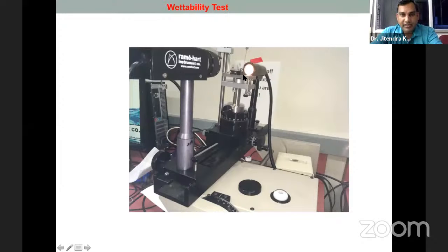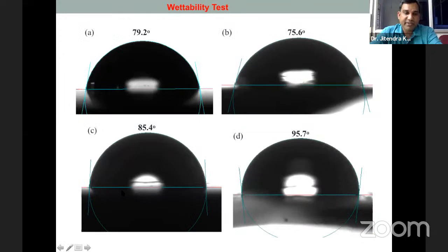That is the density of that particular volume of the drop falling over the surface. And this is the camera, and light falls over the surface, and this camera captures that particular angle, and it gives it to you on this computer. And according to that, you analyze the angle. So these are a few samples of my coating, SU8 coating. I have analyzed that SU8 HBN coating.